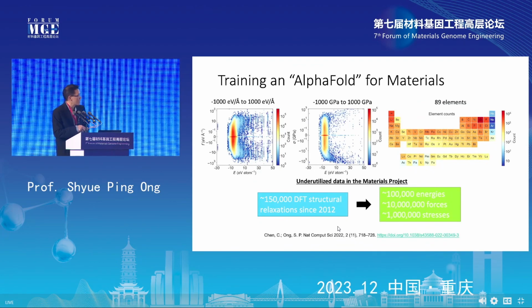took all the data that we have in the Materials Project in terms of structural relaxations. So since 2012, the Materials Project has performed about 150,000 structural relaxations. That means that we have around 100,000 energies, 10 million forces or so, as well as 1 million stresses, and we can throw all this very, very large data set to actually fit one universal interatomic potential that can cover 89 elements of the periodic table, okay?